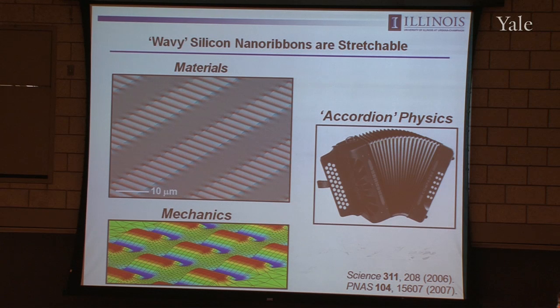So you can go back and forth like that, with a completely linear elastic response to strain, where the modulus is dominated by the stiffness of the underlying substrate. The silicon buckling physics allows it to move in a way that can move with those strains. So it's very much accordion bellows physics. It turns out that the details are quite important to understand, because in these kinds of systems, the mechanics design becomes as important as circuit design. So we're fortunate to be able to work with an excellent theoretical mechanician at Northwestern, and we work with him to develop finite element modeling and analytical models of exactly where the stresses and strains are in a system like this. It turns out it's qualitatively different than an accordion bellows, but in terms of thinking about the physics, this is a good model, and we've gone through the details of that.